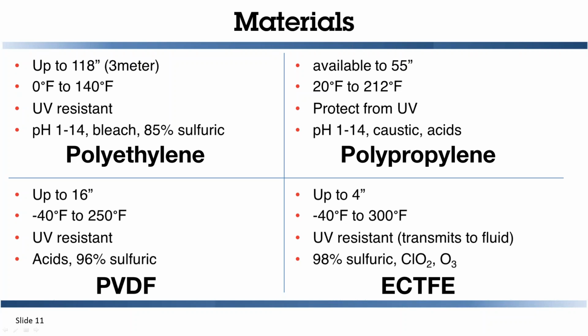PVDF is commercially available up to 16 inch, and has a range of -40 to 250F. It is UV resistant, recommended for acids and up to 96% sulfuric acid. ECTFE is commercially available up to 4 inch in piping systems, with a working range of -40 to 300. Typical applications are 98% sulfuric, chlorine dioxide, and ozone.